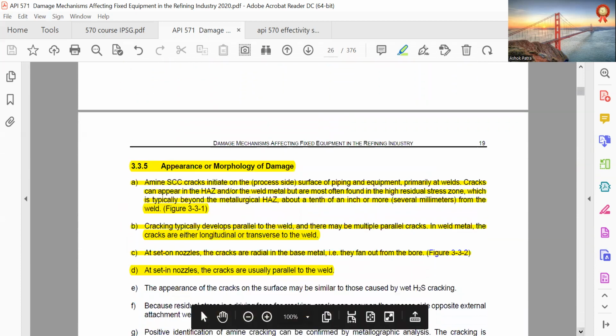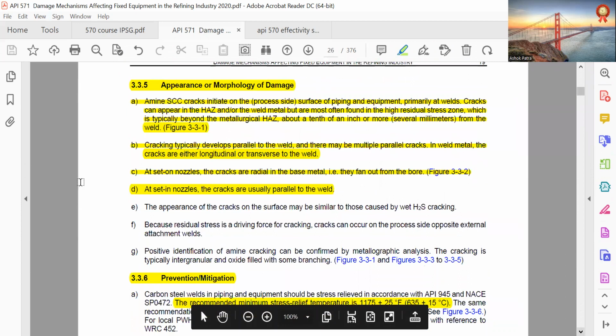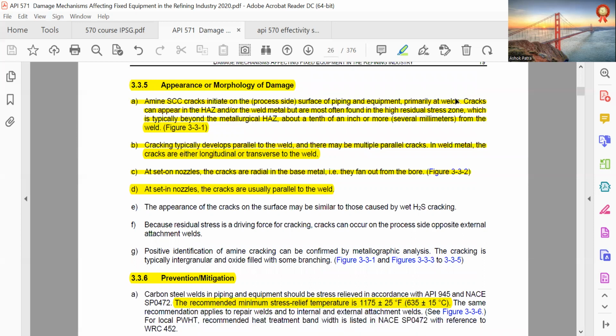Appearance and morphology of damage. Amine stress corrosion cracks initiate on the process side surface of piping and equipment, primarily at welds. Cracks can appear in the HAZ and or the weld metal, but are most often found in the high residual stress zone, which is typically beyond the metallurgical HAZ, about a tenth of an inch or more, several millimeters from the weld. Cracking typically develops parallel to the weld, and there may be multiple parallel cracks in the weld metal. The cracks are either longitudinal or transverse to the weld.